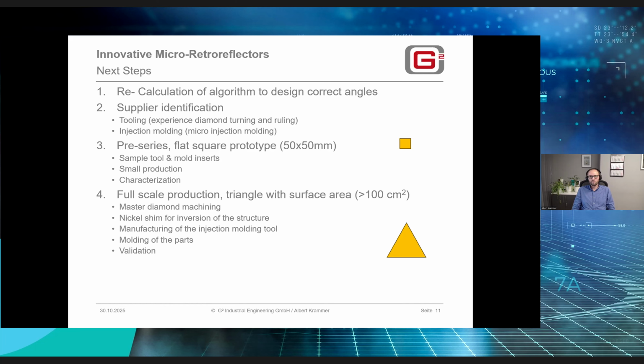We already heard one speech before to get this micro-optics in the tool. One of our approaches was not to have some foils or something like that, which would be more easy by having a round master and the endless foil, but that's not so easy for automotive applications. So our work is now to find a good tooling partner who has experience in diamond turning and ruling to really achieve this 30 micron optics in the steel tools for injection molding. And of course, injection molding, it's also not super simple, and it cannot be done on every machine, and not every supplier can do it. To use these special tools then for the injection molding of the plastic part.